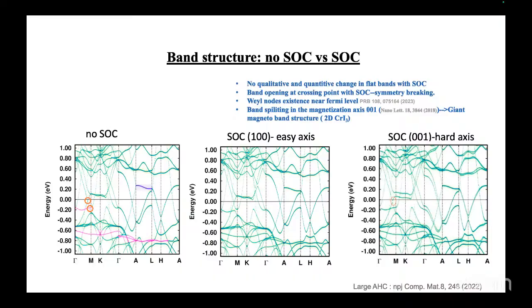We further see, in the hard axis, there is a band splitting coming over. Additionally, the band opening points out a very important phenomenon: how the electron scattering differs with the different spin directions, so along the different magnetization axis, which is also reported in the two-dimensional chromium triiodide system, the giant magnetoband effect, where we see how the electron scattering differs with the different spin-dependent magnetization, which also shows in our system. Apart from this, we do not see any change in the flat bands or the positioning of the flat bands or anything else.